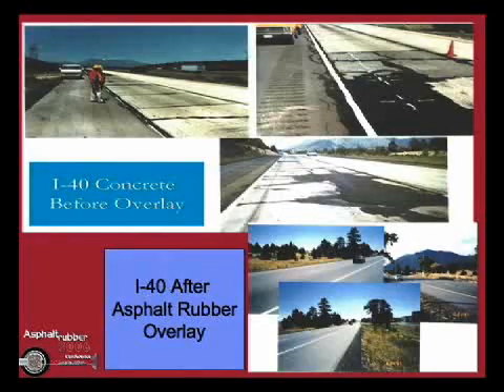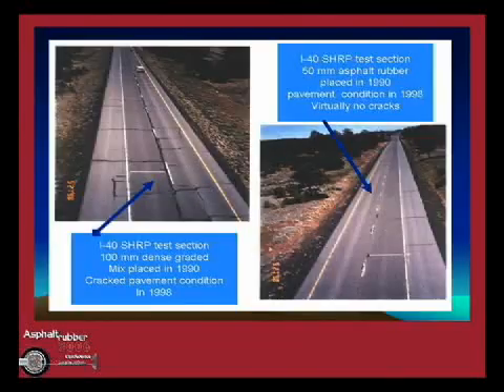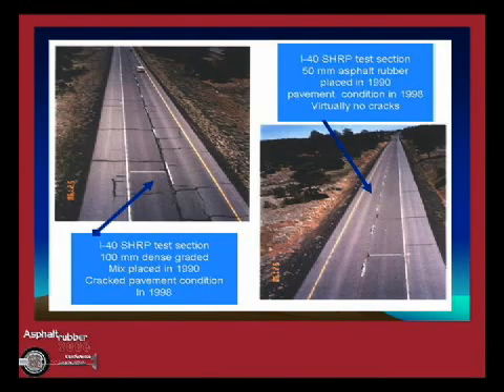This is an example project we did in Flagstaff back in 1990. You see this is an old, badly cracked up concrete pavement. We overlaid it with asphalt rubber, and after a number of years, it performed very well. This is an example test section we did on that same project. You can see here we had a 100 millimeter or 4-inch overlay over that concrete. After 8 years of service, very badly cracked. Here we had half the thickness, only 50 millimeters of the asphalt rubber mix, and very few cracks after that same period of time. Same roadway, same environment. This is in the mountains, so this does get snow in the wintertime.